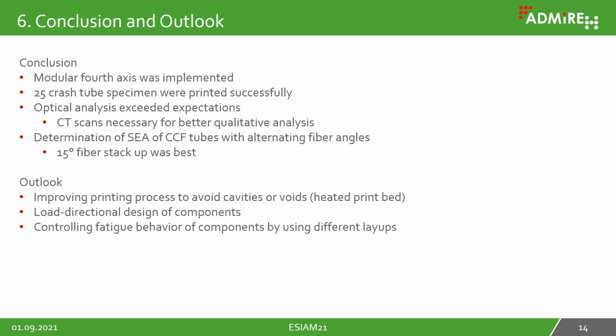To conclude this study, it was shown that a modular fourth axis was implemented into an existing 3D printer, and the possibility of printing on the fourth axis has also been shown. 25 crash tube specimens were printed successfully, and the optical analysis exceeded our expectations, although CT scans are necessary for a better qualitative analysis. Furthermore, the energy absorption capability of different fiber-aligned continuous carbon fiber crash tubes has been determined, and it was shown that the 15-degree fiber stack-up was the best.